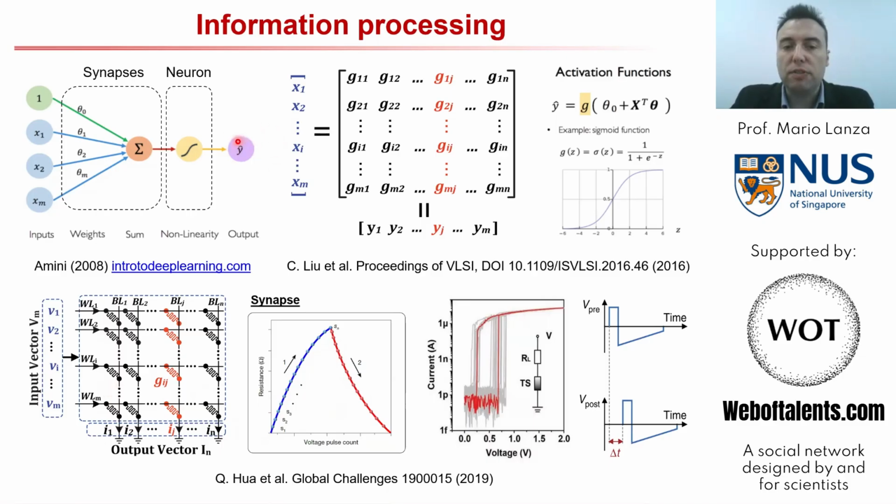And the activation function can also be done with memristors because if we change the materials that form the memristor, the transition can follow a very non-linear shape. And also, this low resistive state can relax, leading to a very well-defined hysteresis, which is something that is necessary for these activation functions.